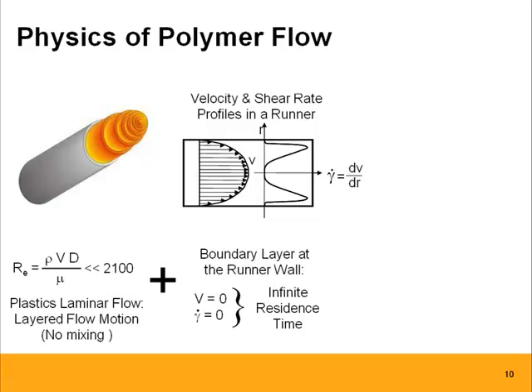In reality, there's a little bit, but just from a calculation point of view, this is what's happening. At the same time, very close to the wall, we have the largest shear rate. Shear rate, by the way, is a good thing for color change. It's almost like rubbing your hands against each other: it creates shear, moves molecules, so to speak, and that helps clean out that area.